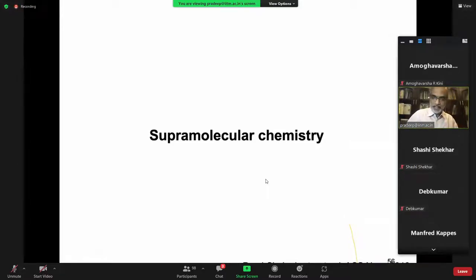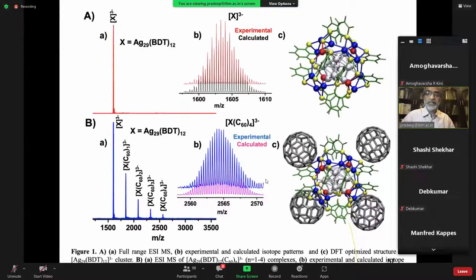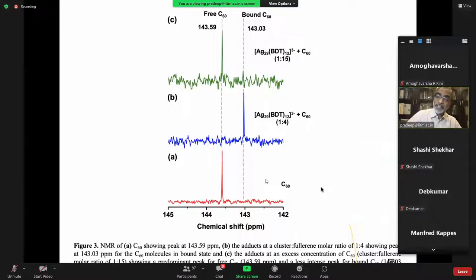Reactions don't stop just there, A and B. There are supramolecular reactions. These clusters are negatively charged. And C60 likes negative charges. So we can create an adduct of this kind. And in this particular case, we can study the shift in the NMR chemical shift of this system. There is a free C60 and a C60 bound to this cluster. You have a different chemical shift. And they are all the same, telling you that all the C60 are sitting on this cluster. In fact, there are four C60 sitting on this. They're all at equivalent positions, etc.